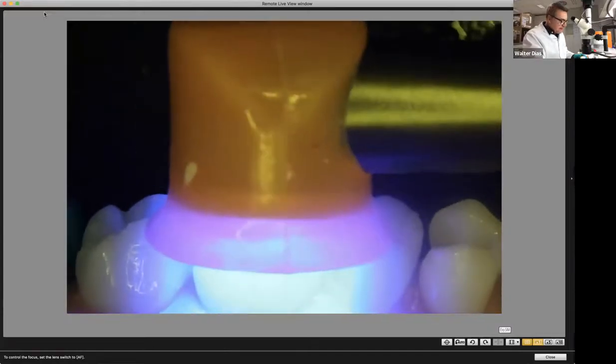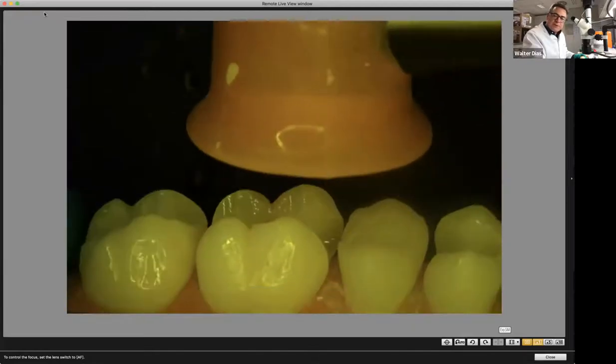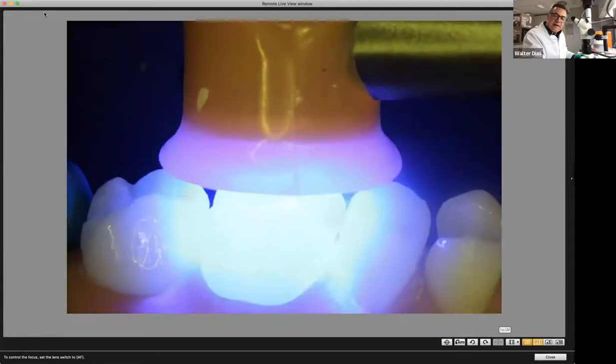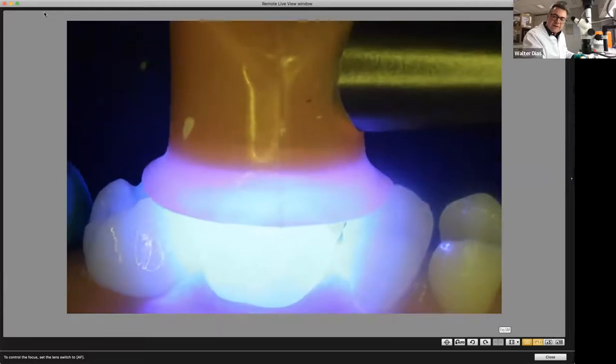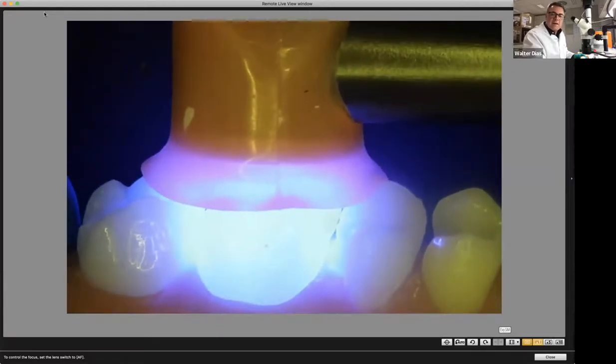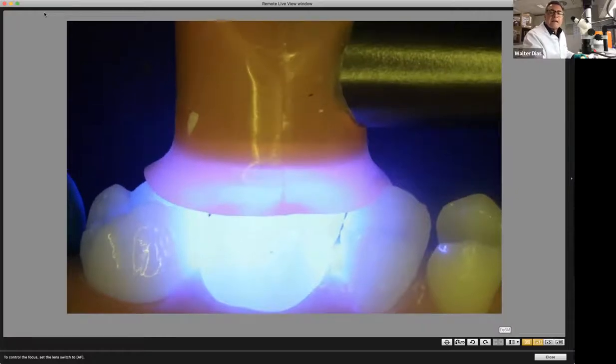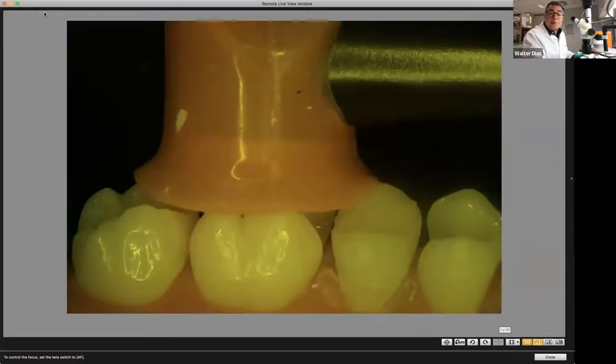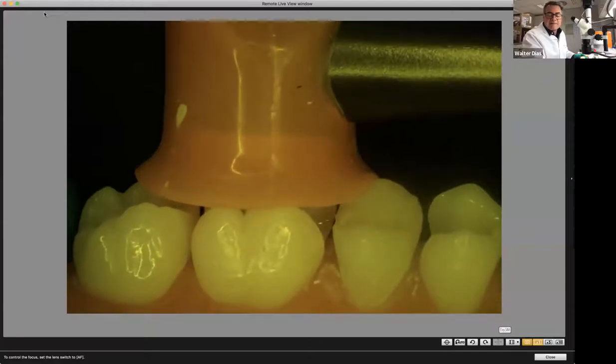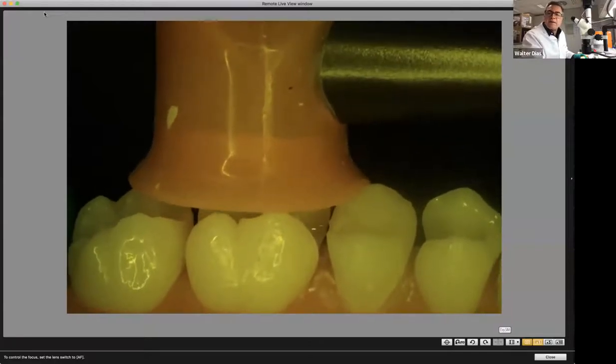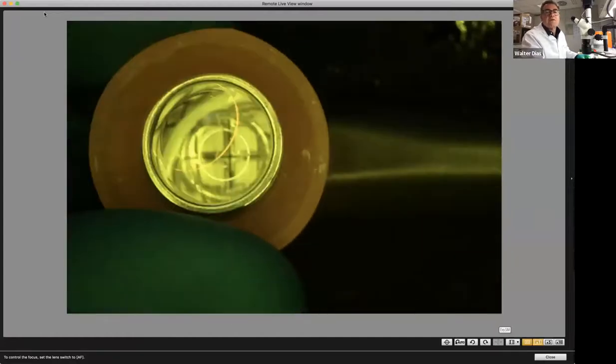Yeah. So the idea is you're going to get closer to the tooth you want to cure, you're going to start curing, and then after a couple of seconds, you can land on the tooth. And the curing time now, it's a very nice surprise, only 10 seconds. That's the curing time recommended by Dentsply for this adhesive, but only if you have a good light. If you're not sure about your light's quality and output, then I would recommend you stick to 20 seconds, the usual 20 seconds.